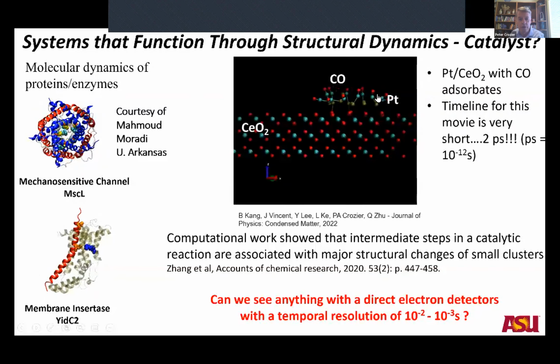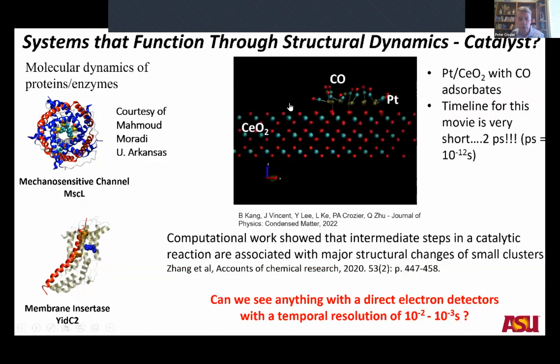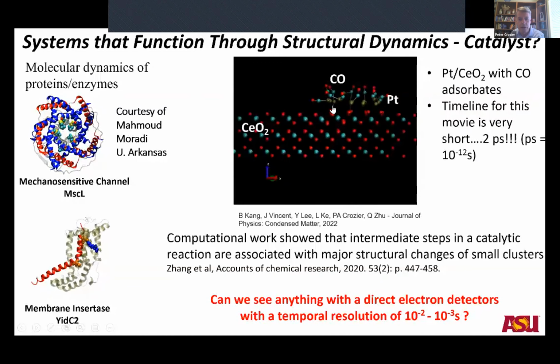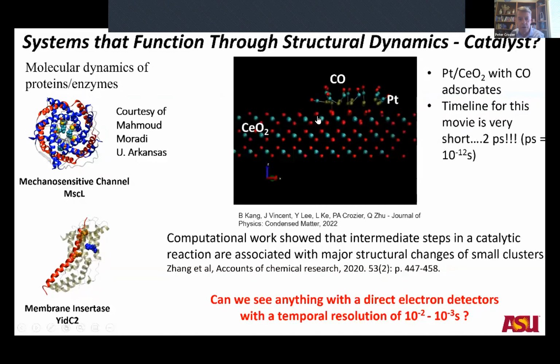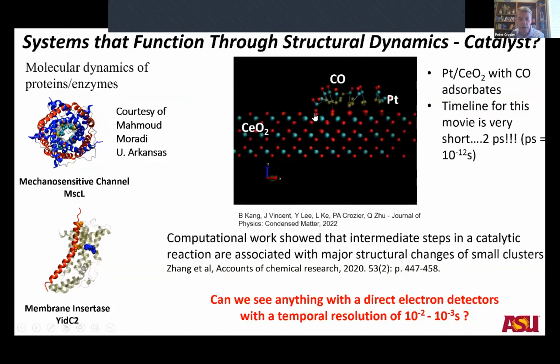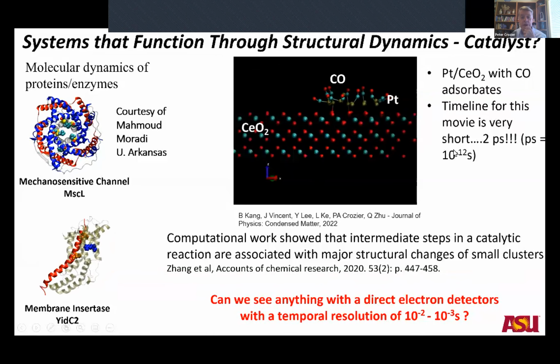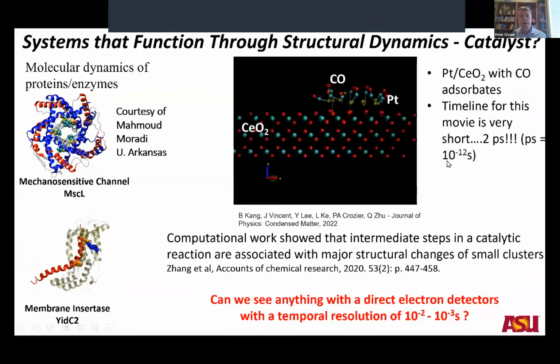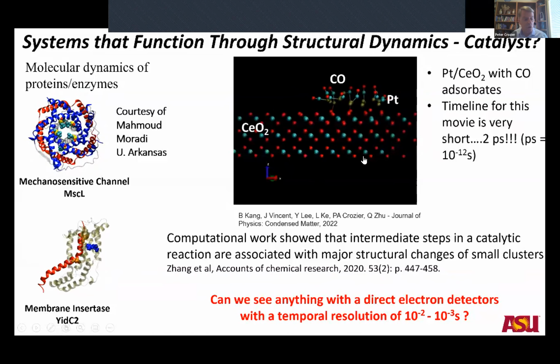And what they've done is they've just put carbon monoxide over the surface of the platinum. And you can see, obviously, there's a lot of jiggling around going on here. And if you look down here, you'll see the CO starting to almost bond with the oxygen and pull it out. We're almost at the transition state there. But I remember Byung-Kun was so excited about this because this ab initio molecular dynamics movie was almost